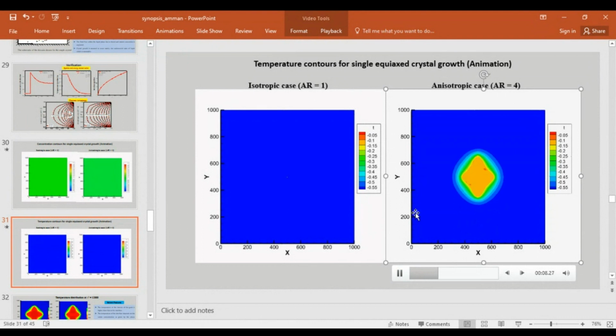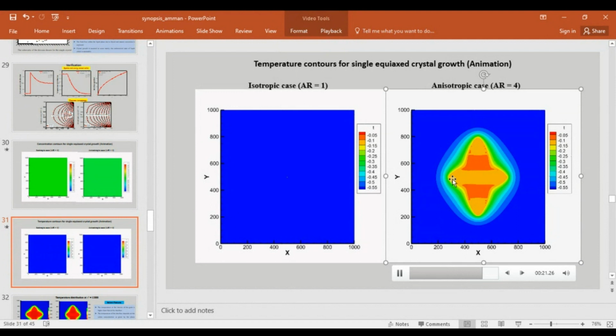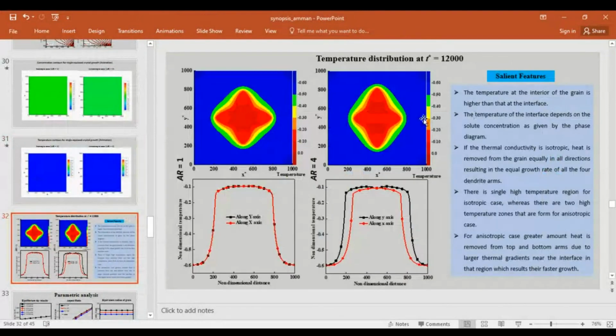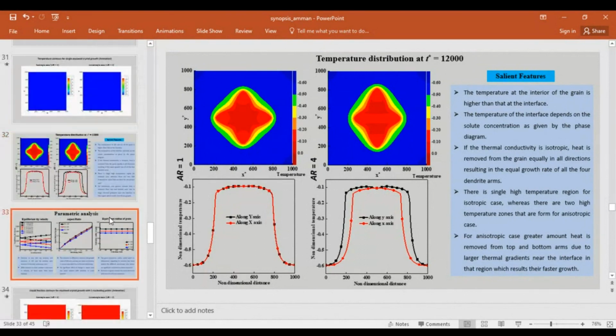You see how the patterns are evolving. There is a formation of two localized high temperature zones here and here. Because of this, the gradients are not much along the x direction, but higher along the y direction, so the growth is faster along y. That has been shown here. Because of the formation of two localized zones, the growth is higher along the y direction as compared to the x direction. So as we increase the anisotropy.